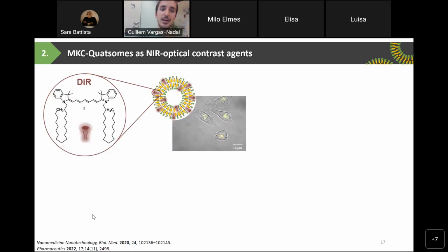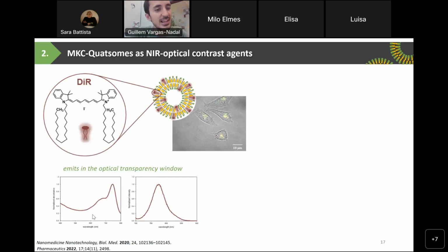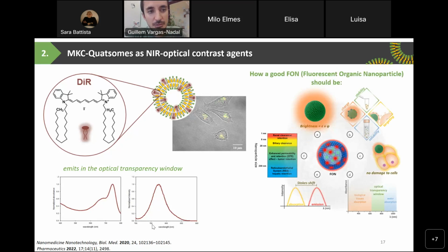And another property of these quatsomes is that they can be loaded with some dyes. In this case, we loaded these MKC quatsomes with a DIR dye. This DIR dye emits in the optical transparency window, which means that it emits in the near infrared region, as you can see here, after 700 nanometers. And this is a good thing, because a good fluorescent organic nanoparticle should emit in the optical transparency window, because in this case the noise and the autofluorescence is reduced. So here we will not see the autofluorescence of other organs and tissues.